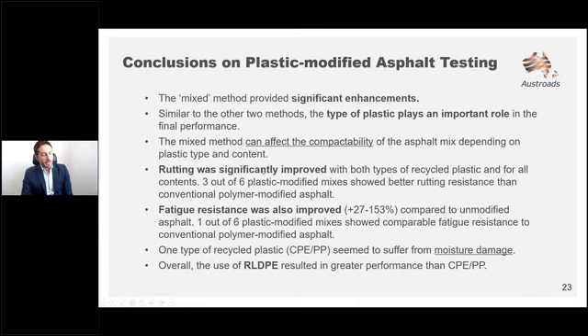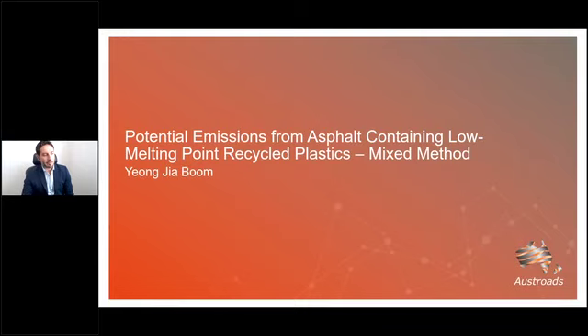So out of the 2, probably the RLDPE was better. That was probably because the mixing temperature was equal between the 2 of them. If plastics that contain polypropylene are added, it may be suggested to increase the temperature a bit higher compared to when there is only polyethylene in it. One type of recycled plastic, the commingled version, seems to suffer from moisture damage, as we showed you through the TSR ratio. I'll now hand it over to Yongjia to talk about the potential emissions from asphalt.